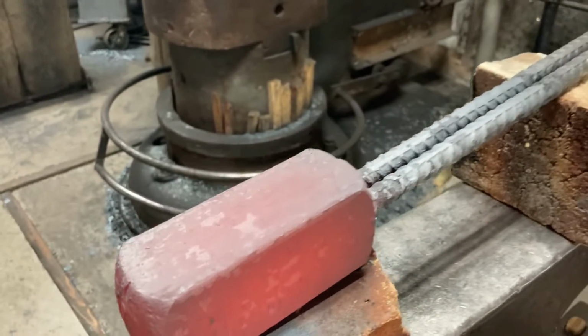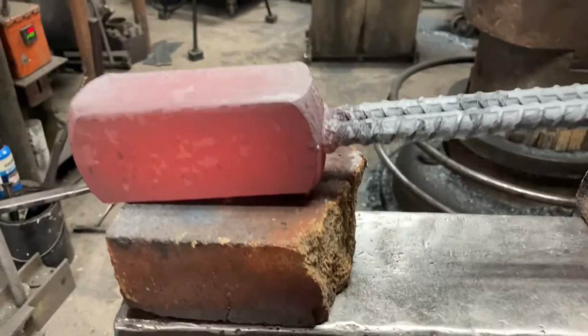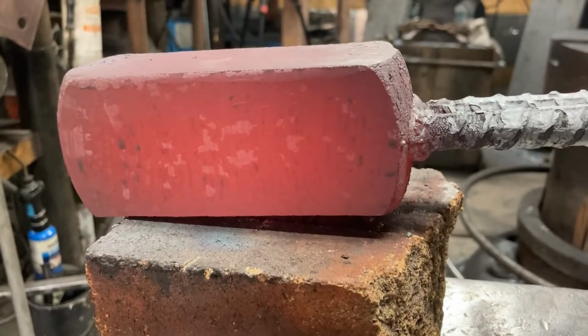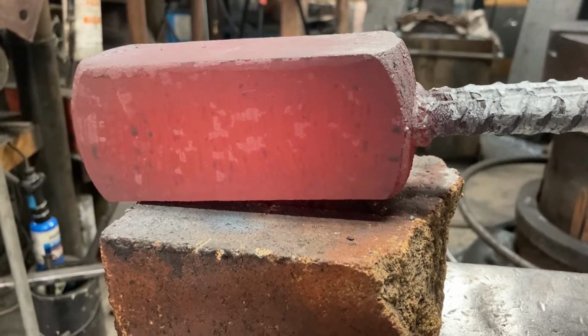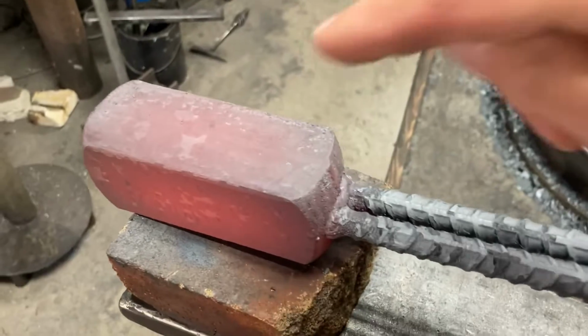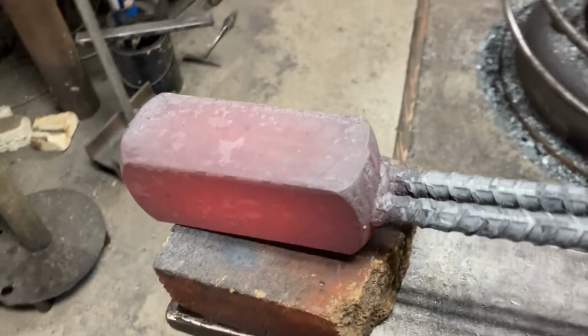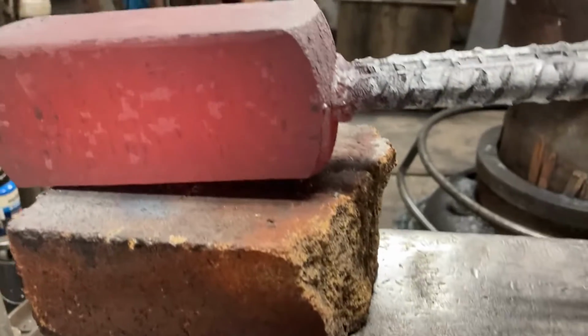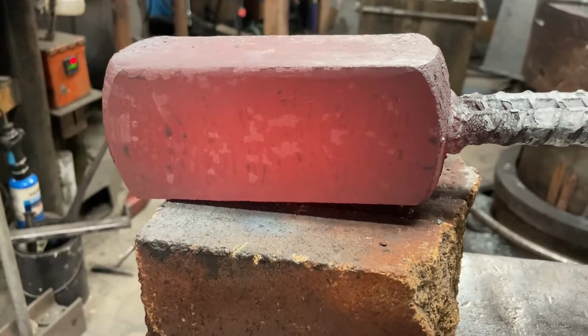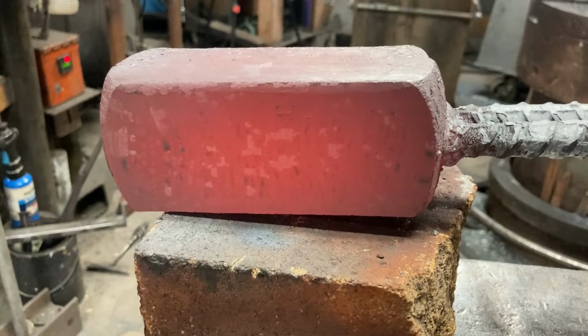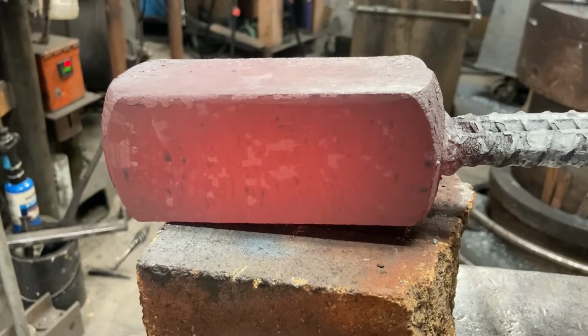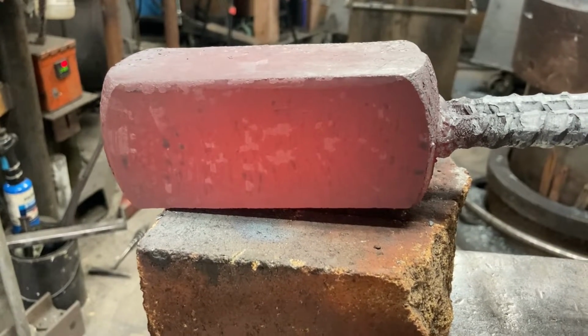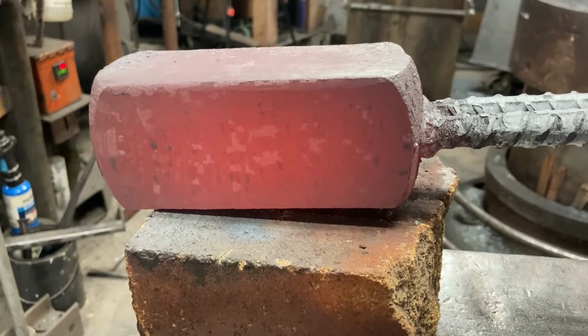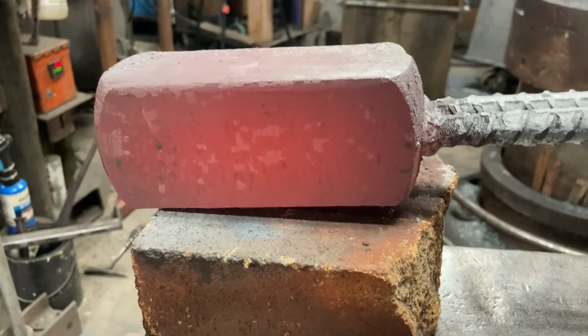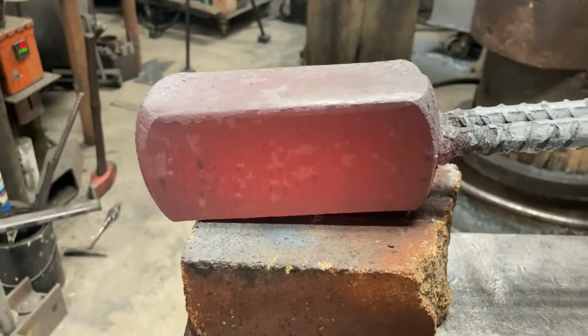And we got some good dimensions here. So the big flat side here is actually the non-grain side. All the pattern is in here. So when we cut cookies, they'll be going off like that. So we're about 2.5 to 2 3/4 inches here. So we'll be able to cut at least 3/4 inch thick slabs off of there, and then have room for a saw blade and a little grinding. So that's perfect.